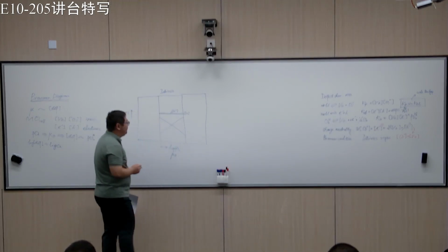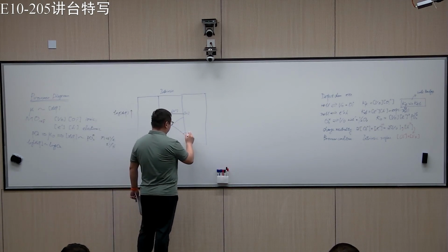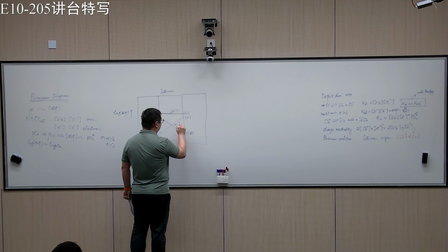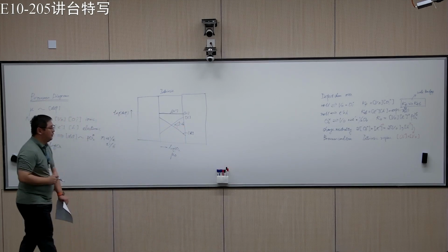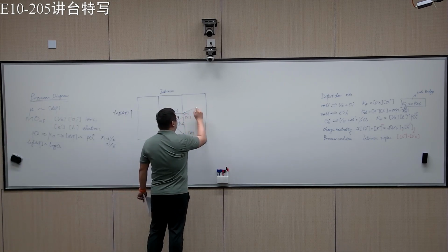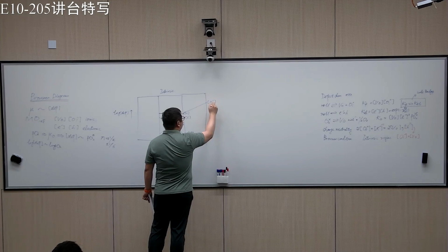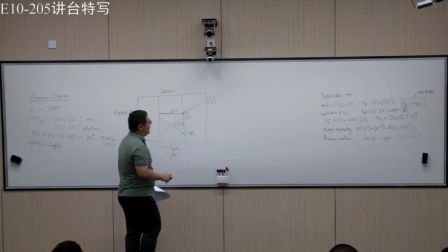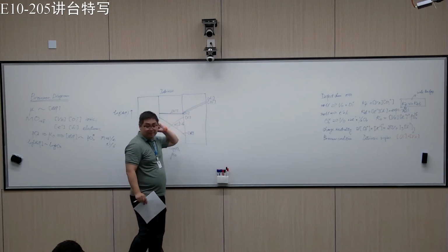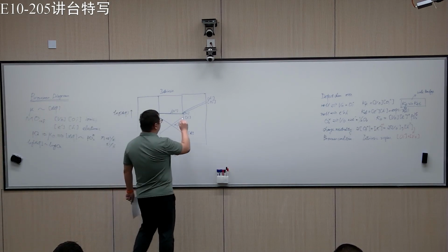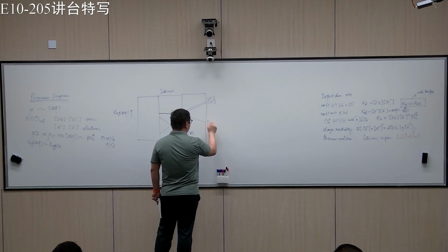Okay, something like this. So basically, this is the hole. Sorry, this is the electron. So this is the hole, and we have the slope to be 1/4. And of course, if we go to the oxygen-rich regime, we can imagine that the amount of oxygen interstitials goes up and will be charge balanced by holes, because negative oxygen interstitials have to be charge balanced by positively charged defects. Then the oxygen vacancies basically go here.